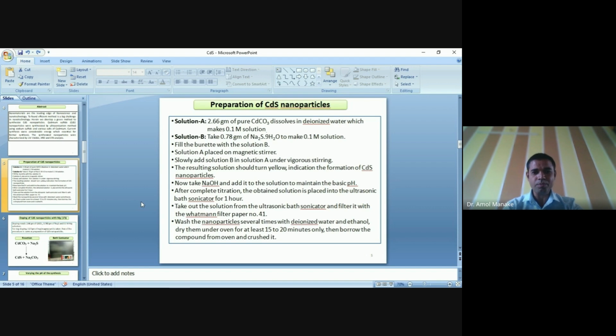Then after washing, I see lots of researchers who synthesize cadmium sulfide nanoparticles calcinate them for 6 to 7 hours. But by using the ultrasonic bath sonicator, there is no need to go for 6 hours of drying in the oven. Only 15 to 20 minutes are essential for drying the product. There is no water molecule in the product.